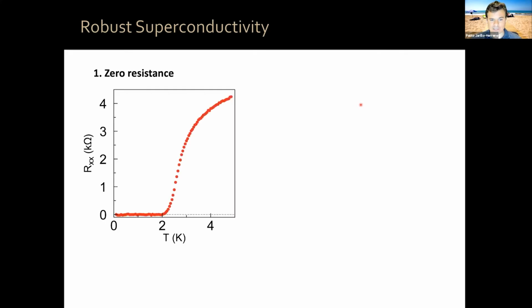So for that, you want to see zero resistance, and indeed, resistance drops to zero. You can fit this with the Halperin-Nelson formula. It tells you the Berezinskii-Kosterlitz-Thouless transition, which in this case is about 2.3 Kelvin. Sometimes we quote 50% of the normal resistance in this two-dimensional community, and that's 2.9 Kelvin.